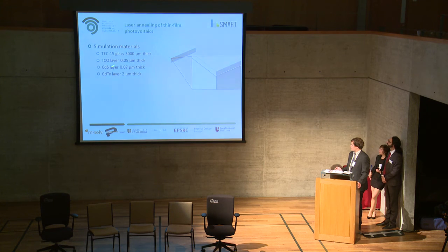So the next part of this is laser annealing itself. We're using a laser to post-process the sample after the cadmium telluride has been deposited. For this, we created heat transfer simulations in order to analyze in advance what different laser beam profiles would achieve. And we created this sample, which has a TEC15 glass layer, 3,000 microns, and then the 3 coated layers of transparent conducting oxide at 0.05 microns, cadmium sulfide at 0.07 microns, then cadmium telluride at 2 microns.